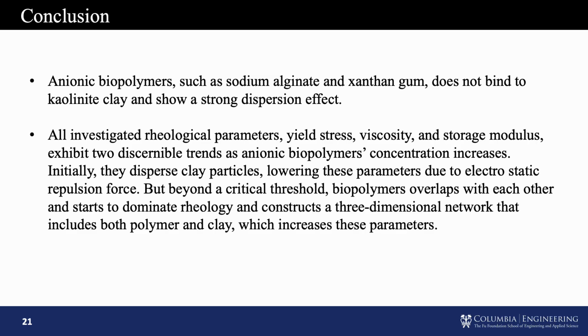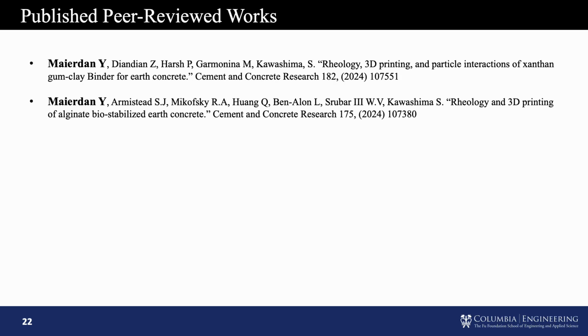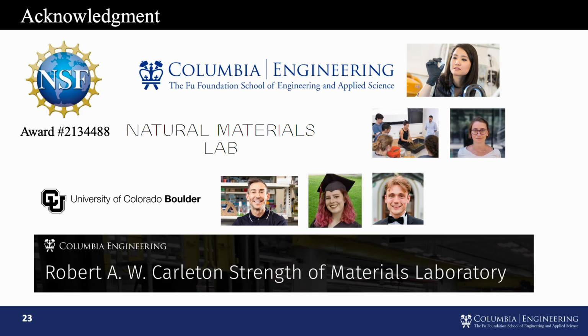With these polymers, you can enable continuous and smooth printing of the material with a high solid volume fraction, which eventually increases the compressive strength and reduces the drying shrinkage of the material. And today's presentation comes from these two papers published in CCR, one of them about sodium alginate stabilized earth, and one of them about xanthan gum stabilized earth. If you're interested, you can read more details from these two papers.